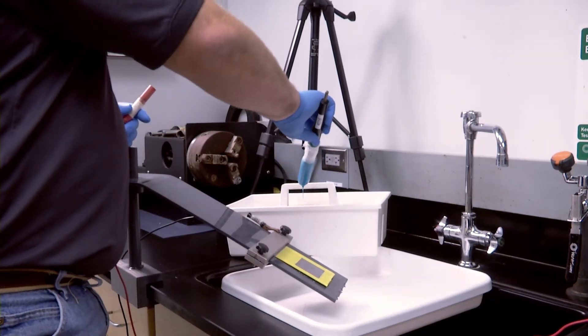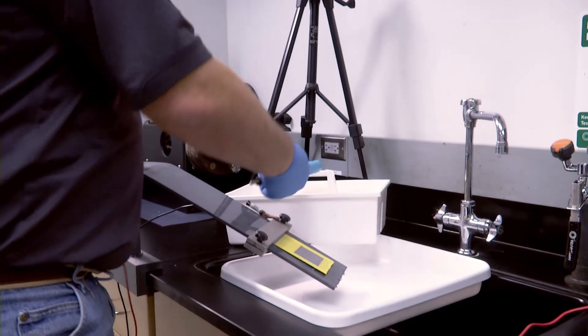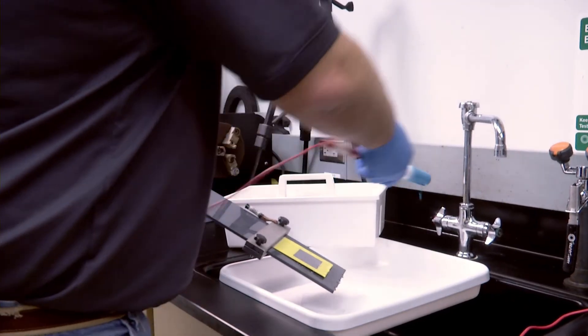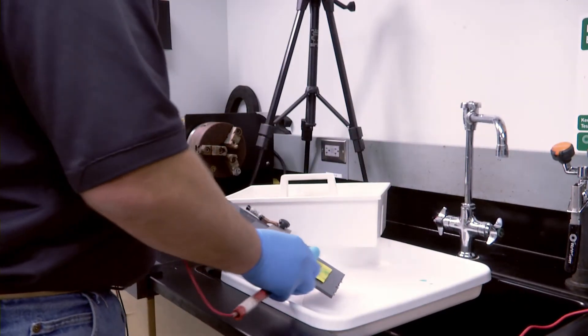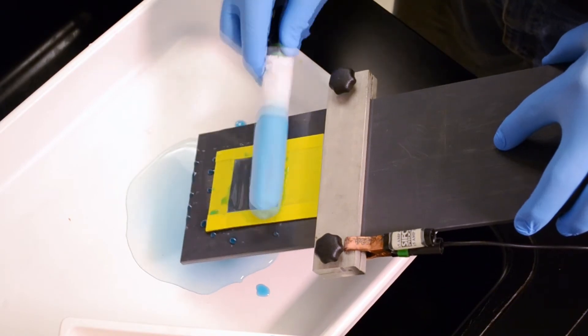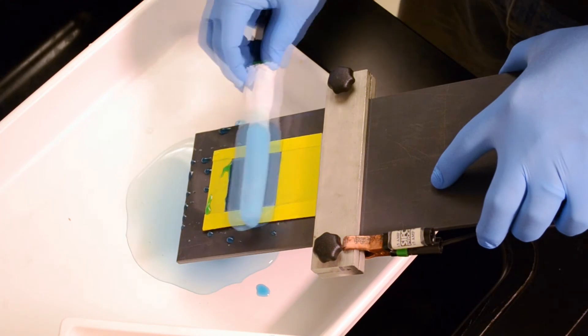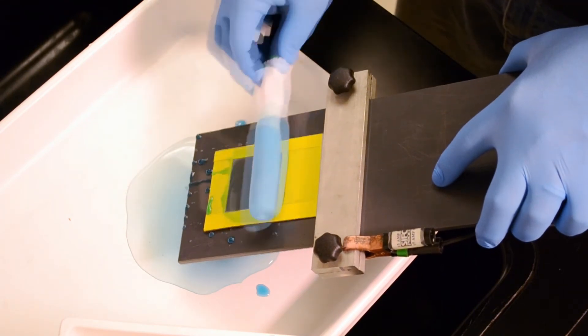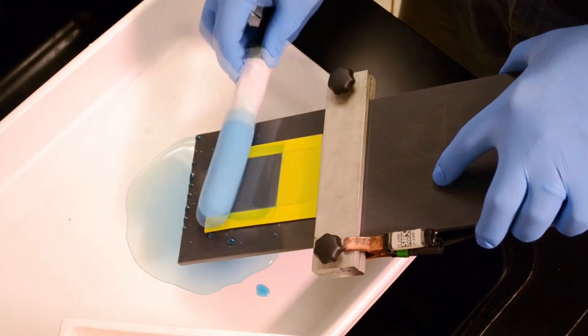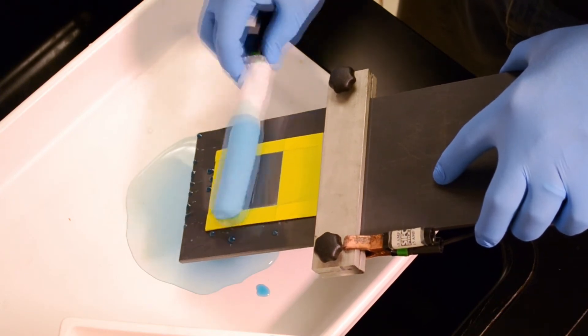Note that the selective plating tool is applied to the workpiece with current. The selective anode is moved uniformly over the part and in a very brief period of time, a visible layer of nickel is deposited. The anode is repeatedly dipped into the fresh solution every seven to ten seconds and then continuously moved on the part until the calculated amp hour value to achieve the deposit thickness of five ten thousandths of an inch has been reached.